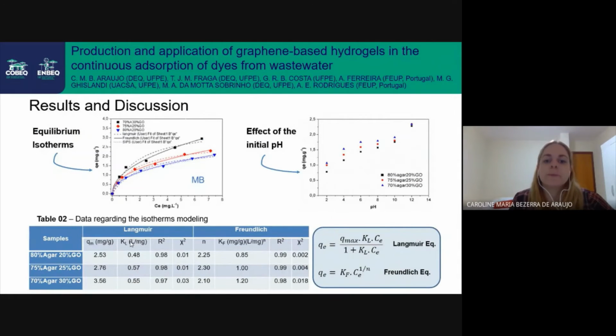We proceeded with batch adsorption experiments using methylene blue in water. And for all the 3 samples, as we put more graphene oxide in the composite, the adsorption capacity increases. On the other hand, evaluating the effect of changing the initial pH of the methylene blue solution, the adsorption capacity also slightly increases as we increase the pH. And from the fit of Langmuir and Freundlich models to the equilibrium isotherms, it is noted that both Langmuir and Freundlich isotherms were well fitted with the data.